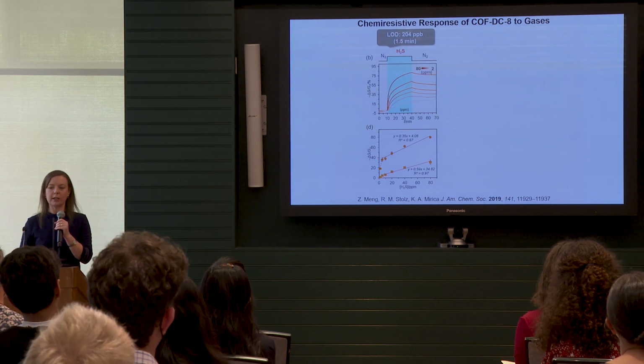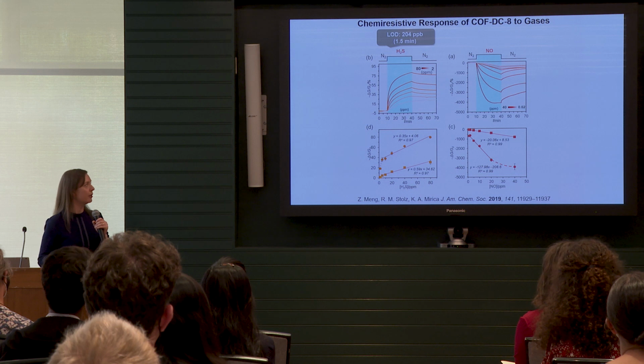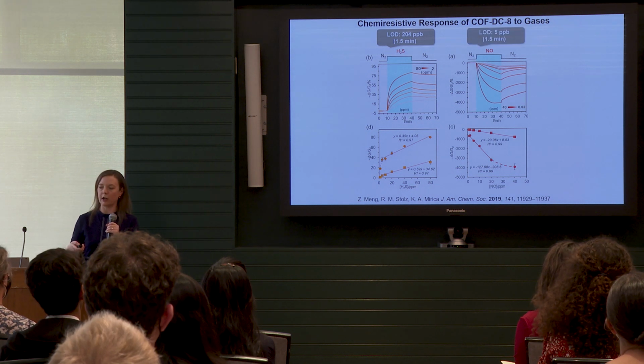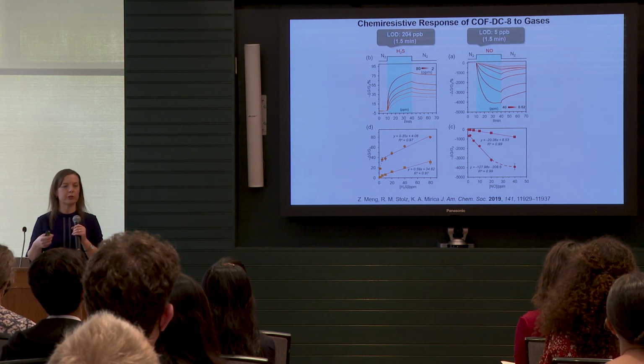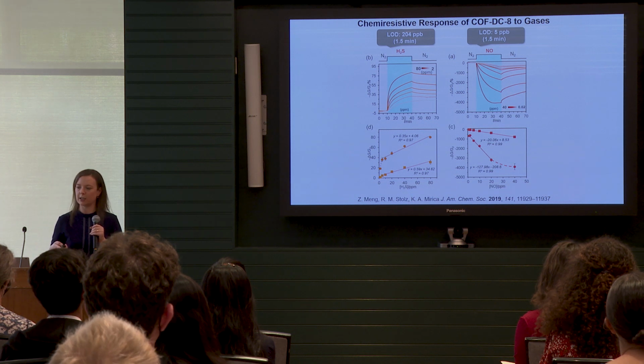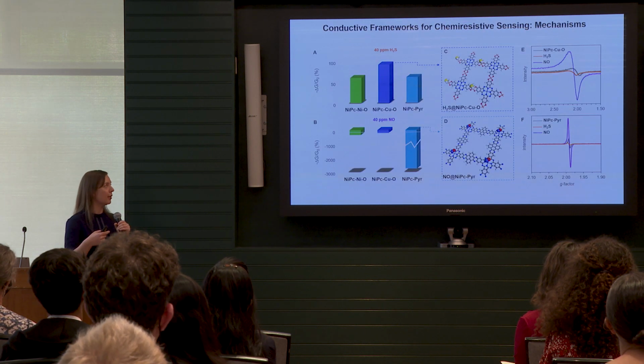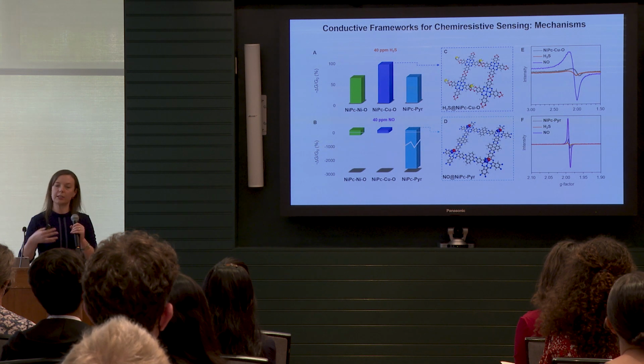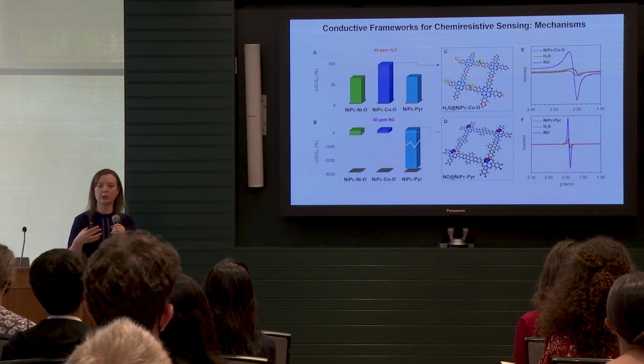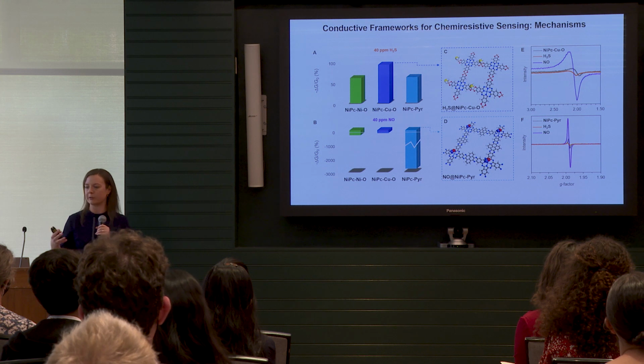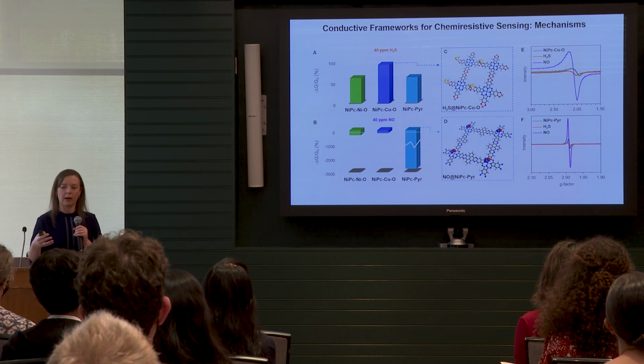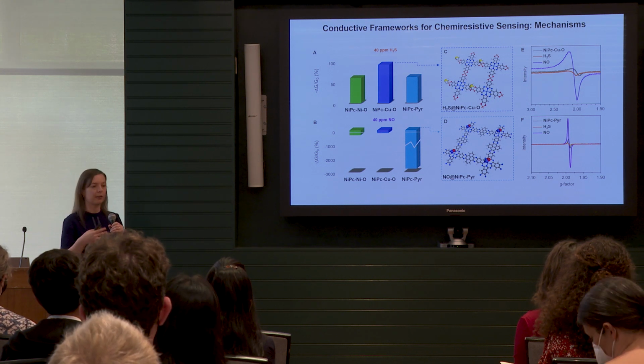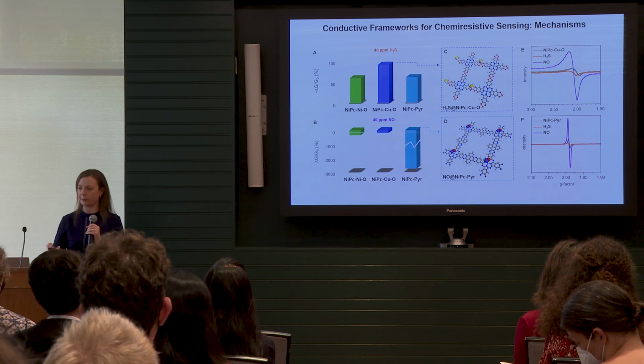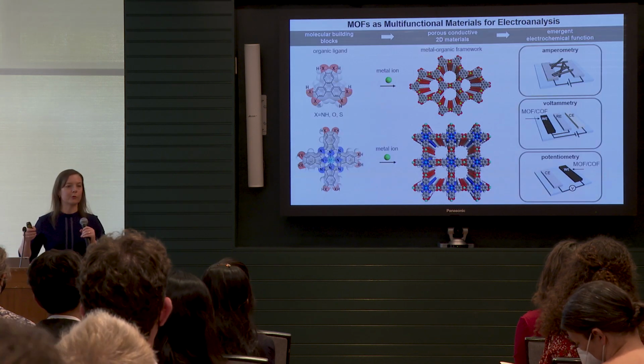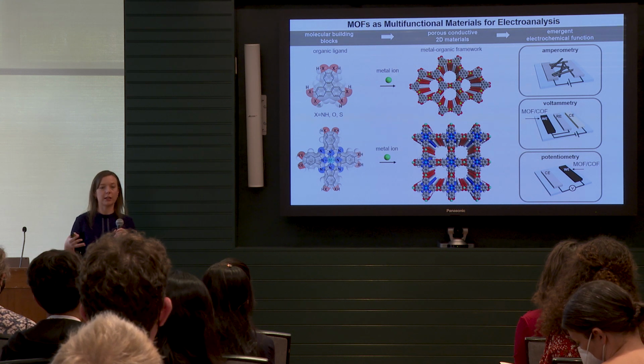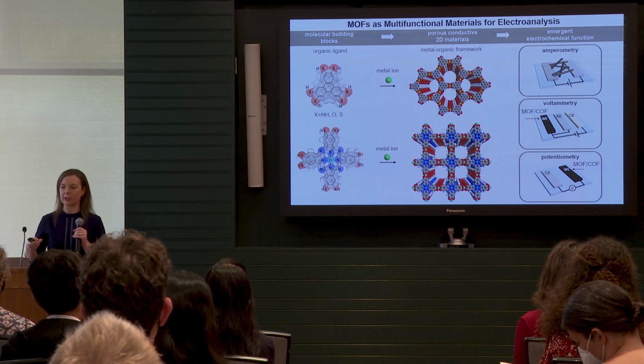In terms of sensing, we take a little bit of a hit for hydrogen sulfide, but we maintain sensitivity to nitric oxide. And so what that structure-property relationship analysis tells us is that the presence of metallic nodes, specifically that are copper-based nodes, is really important for obtaining good limits of detection for hydrogen sulfide, while for nitric oxide, the nickel-based framework does the job. So we can glean structure-function correlations by studying structurally analogous materials.